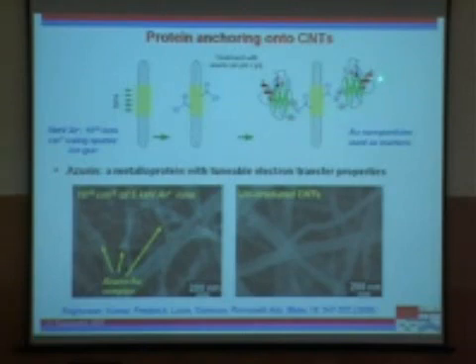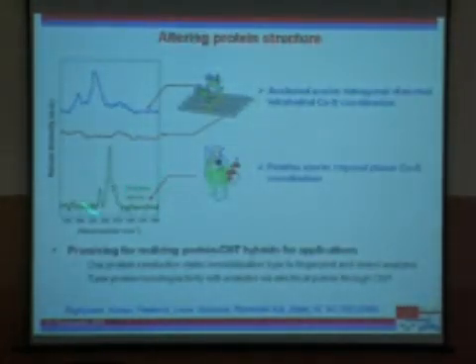Suppose I use an electroactive protein. Okay, this is actually azurin. It has a very high dipole moment, and in this particular case, we attach this by electrostatic interactions to certain segments of carbon nanotubes. And I'll show you that when we did Raman spectroscopy, what we found was that pristine azurin shows this particular signature with certain kind of coordination, or basically certain kind of shape. Which you can relate to a certain kind of dipole moment. Now, if I have that attached to carbon nanotubes, you see a different signature. Okay, and what that means is its structure is distorted, and hence its dipole moment is also distorted. Okay, now the IV characteristics of the carbon nanotubes should be modified, or should be distinguishable in these two cases.